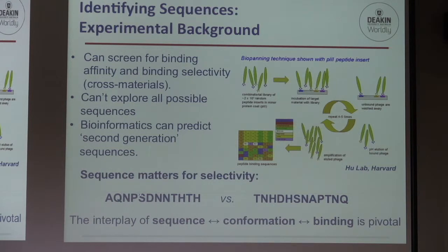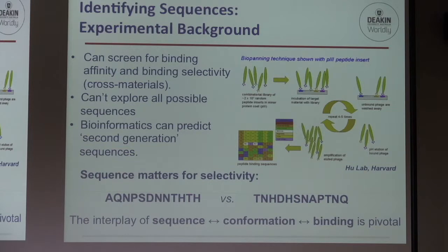Yet this sequence here on the left will bind exclusively to silica and it will not bind to gallium arsenide. You mix up the sequence and it will bind to both. So it completely abolishes the selectivity. So what this tells us is that this interface, this recognition between the biomolecule and the peptide, is not just about, well, I've got two histidines and a proline and that's what's working. It matters a great deal, because if you mix up that content you get a very different binding affinity.